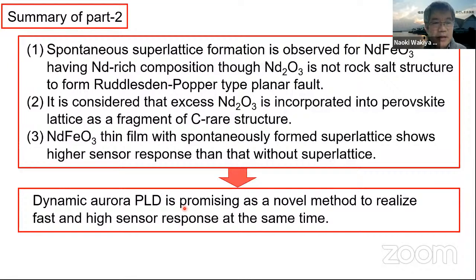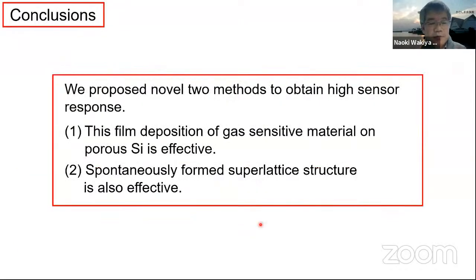So, summary of part two: the spontaneous superlattice formation is observed for the neodymium ferrite having neodymium-rich composition. So Nd2O3, I'd like to skip this one. And so the neodymium ferrite thin film with spontaneously formed superlattice shows higher sensor response than that without superlattice. So dynamic oblique PLD, our method, is promising as a novel method to realize fast and high sensor response at the same time. So this is a conclusion.